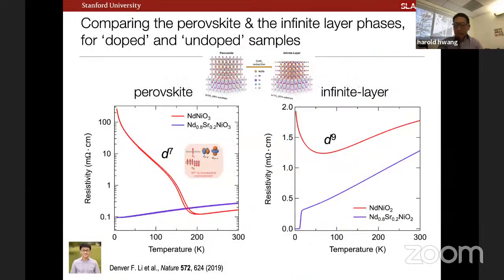So let me start with a kind of a summary of some of the basic properties that we see. Let's start from that perovskite form. You see that the resistivity of the neodymium nickelate, nominally undoped system, has this well-known first-order metal insulator transition. And as I previously alluded to, consistent with old results, if you hole dope the system, you suppress this metal insulator transition. And if we go from O3 to O2, we find something rather different. The undoped system is kind of intermediate. It's neither really a good metal or an insulator. You have this weak, approximately logarithmic upturn, but for the doped compound, you indeed see that this thing goes superconducting.